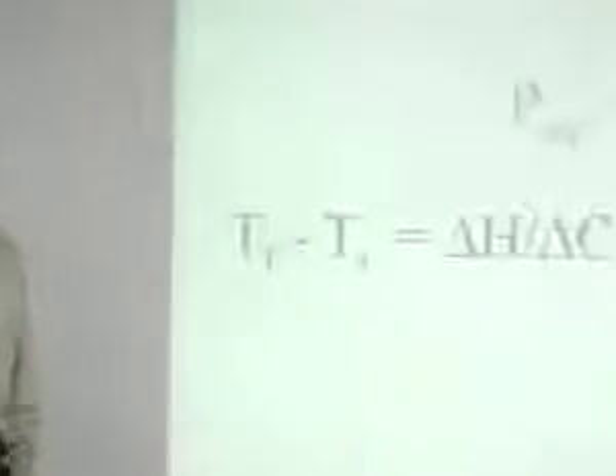The TG is not heating rate dependent. Okay, the peaks in your overshoots and things like that are heating rate dependent, but those aren't what the fictive temperature is. So you have to be a little careful, but they are cooling rate dependent. And the cooling rate dependence is the same as what I mentioned about 3 to 5 degrees per logarithmic decade of rate.